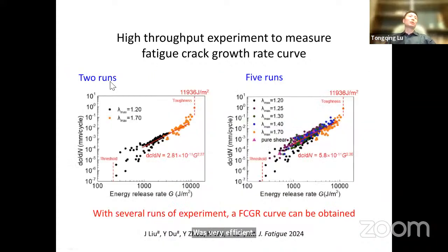After 2 runs of experiment, one with a stretch amplitude of 1.2 and the other 1.7, we can see we almost obtain a complete fatigue crack growth rate curve, including the toughness and the threshold. Only 2 rounds of experiment. If we do more rounds, for example 5 rounds, we have a lot more data here, and the prediction could be a little more accurate.